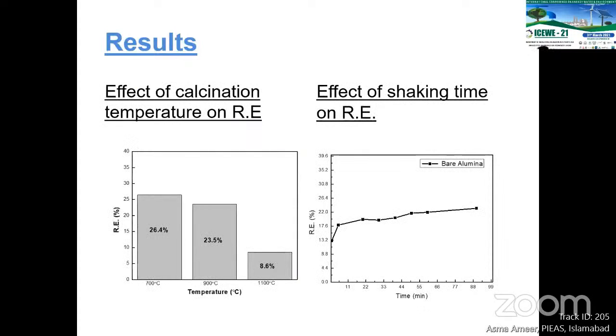Next is the effect of calcination temperature on removal efficiency. We can see that removal efficiency was highest in the case of AACH calcined at the lower temperature, 700 degrees C. The possible reason is that at higher temperature agglomeration takes place, whiskers are agglomerated and intraporosity decreases, and this might be the reason for the lower removal efficiency at higher temperatures.